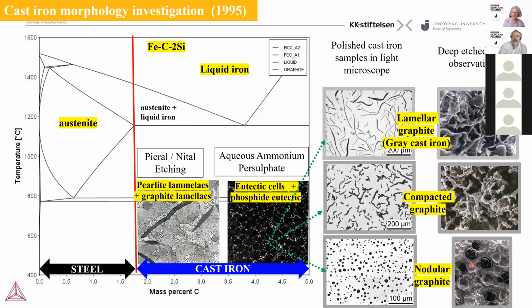To understand the metallic matrix more deeply, we have mainly two methods to prepare the samples. One is the picral etching, the other the nital etching method. As you can see in these pictures, it was possible to see, besides the graphite particles, the metallic matrix. In this picture, you can see pearlite grains and pearlite lamellas.